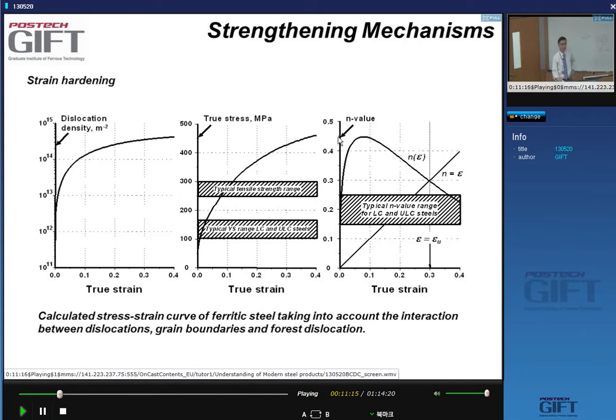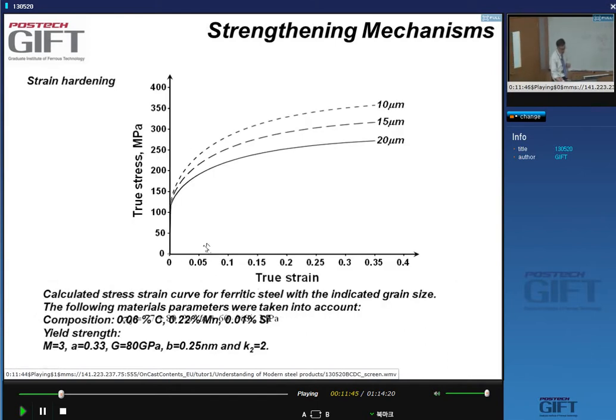This n value, when in undergraduate materials mechanics they introduce this, they say, well, n is a constant. It isn't. This n actually changes a lot during the deformation. And the reason is because of the changes in your dislocation density as you deform the material. So this is, for instance, a calculation of a stress strain curve that's entirely theoretical, and where you can include, for instance, the effect of the grain boundaries.